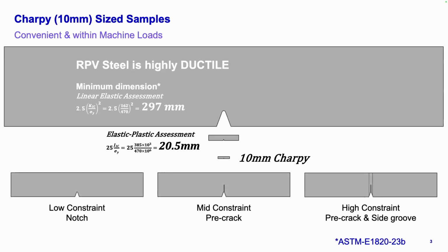Looking around that sort of thing, I've investigated three different sorts of constraints with my Charpy size. So 10 millimeters, 10 mil by 10 mil by 55 mil. I've got low constraint, that's just the V notch, a typical Charpy. I've got a medium constraint where I've pre-cracked by fatigue. And then I've also got a high constraint, which is pre-cracked and with side grooves on the side. Interest here there is how does this affect my ability to do fracture mechanical testing using these sub-size samples?